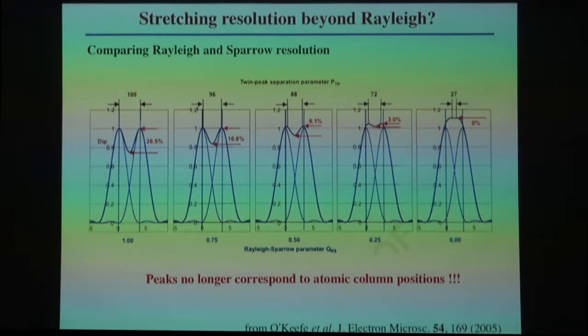But O'Keefe also pointed out one other problem, just to get a little bit more refined. Here is the Rayleigh criterion, where you have the peak and the minimum of one diffraction disk, and here you have the peak and the minimum. Under the Rayleigh criterion, the maximum and minima are exactly overlapping. There's a drop of intensity of 26.5%. But as you move the two peaks closer together, you are able to resolve them, as it were. You can still see a bright peak and a bright peak.